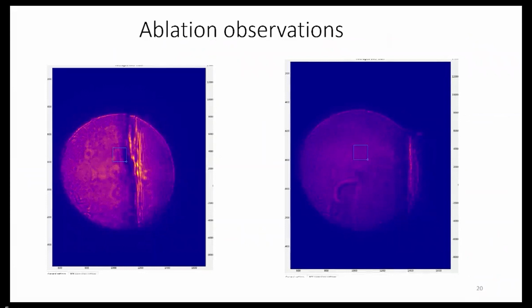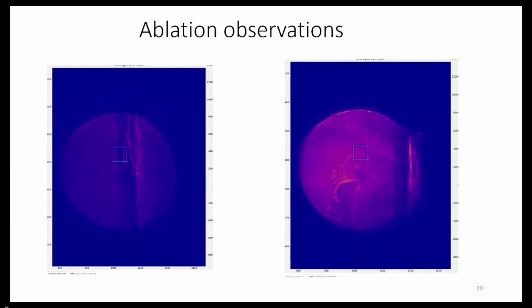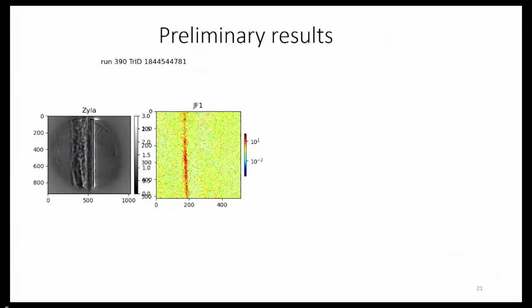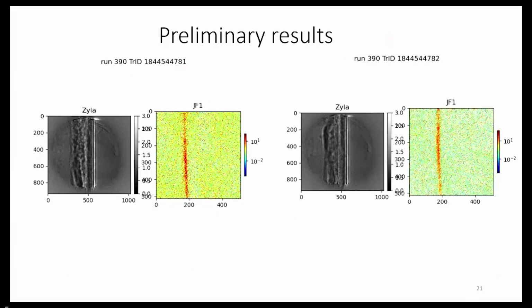So here's a picture we get from the measurement. Here's the surface. And what you can see here, we have just put the laser on all the time, and you can see that the surface starts moving and ablation occurs. So here's a result we get. It's a preliminary result, it needs more post-processing, but here's the surface, here's the initial state, and here you can see that something is happening. So this could be the shock wave or a consequence of the shock wave.